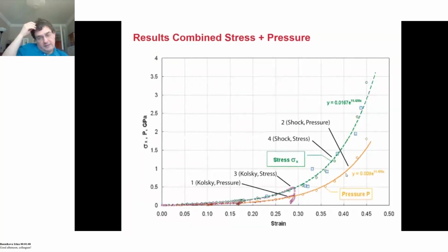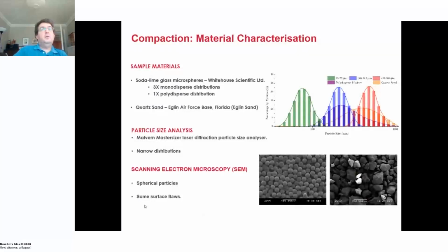And you find that there is a curve on which this particular sand sits, and it's one continuous curve. So you'll see continual behavior. There's no sudden change in the dynamic regime. It's all fitting onto one curve. So having identified that one of the main differences is in the initial compaction, we decided to follow this up by doing some studies involving sand, but also spheres.